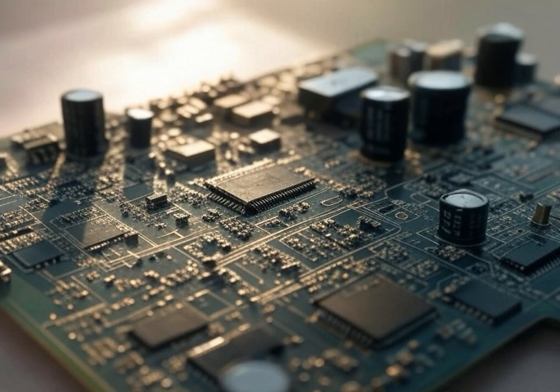But then, and this is where it gets tricky, you have to fire these pastes at really high temperatures, often exceeding 550 degrees Celsius. Wow. This is to burn away the organic compounds and also to fuse those metal particles into a conductive film. So that high temperature firing sounds like a major limitation, right? Oh, absolutely. It restricts you to only using substrates, like I said, glass and ceramics, that can withstand those really high temperatures.